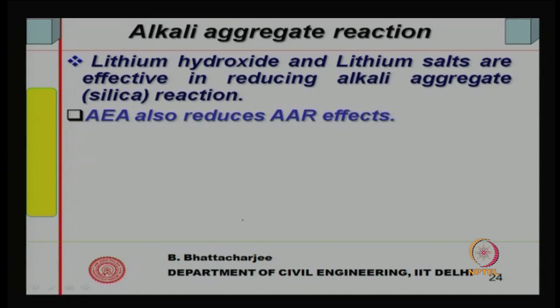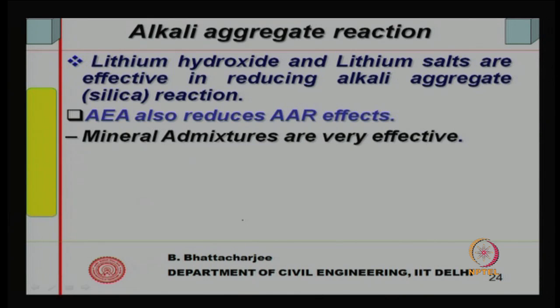For example, lithium hydroxide or lithium salts are effective in reducing alkali aggregate reaction, because sodium, lithium, potassium belong to the same group in the periodic table. So, lithium replaces sodium, and lithium silicate gel is not gelatinous, so it does not cause any expansion. Air entraining agent also reduces the alkali aggregate reaction effect somewhat, because the air voids available can take up the expansion.